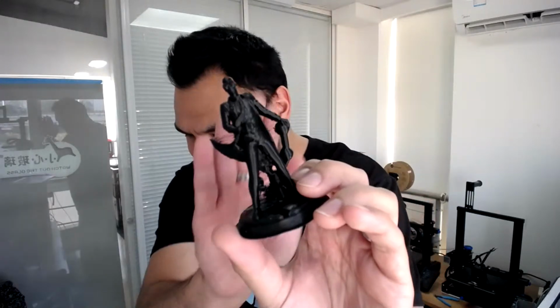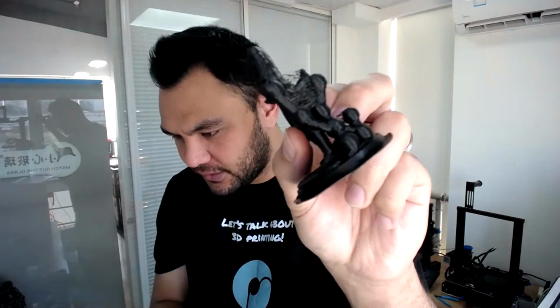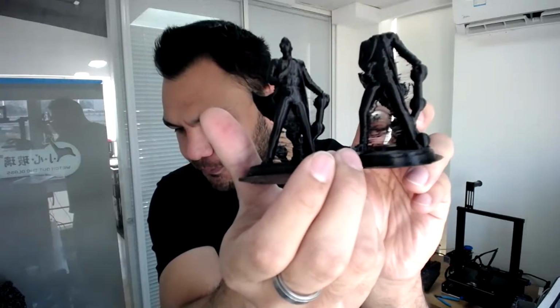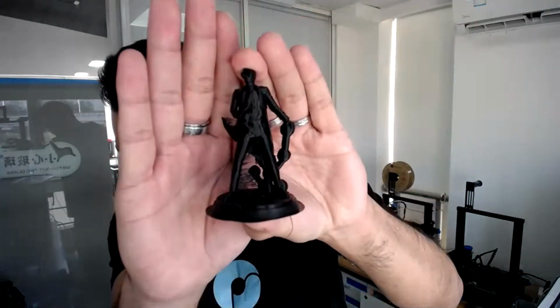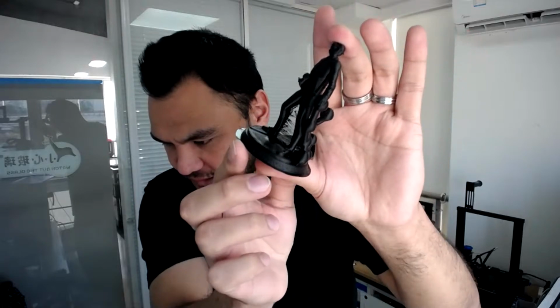So what I did is I tried to see if we could get good quality out of nylon, even though it has absorbed moisture. Well, it was not good in terms of stringing. So this one is a little bit better. This is the same spool that produced this one and this one, but you can notice that the surface quality on this one is much, much better. But the stringing is not. It's much better, but we are still far from having something that you don't have to clean up, if I put it this way. But the surface quality is much better, even the first layer and the top layer.